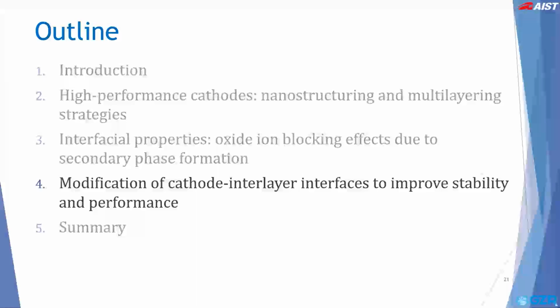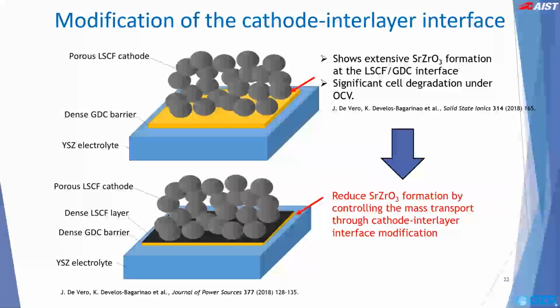Next, I will discuss some results on the modification of interfaces to improve stability and cell performance. As we have seen, the formation of the strontium zirconate at interfaces is one of the major issues concerning the long-term stability of SOFCs. Here, with the aim of controlling the interdiffusion phenomenon and thereby reducing the strontium zirconate formation, the last topic deals with the modification of the interface via a dense LSCF layer in addition to the dense GDC barrier layer prepared using PLD as a means to control the mass transport across the cathode and interlayer.